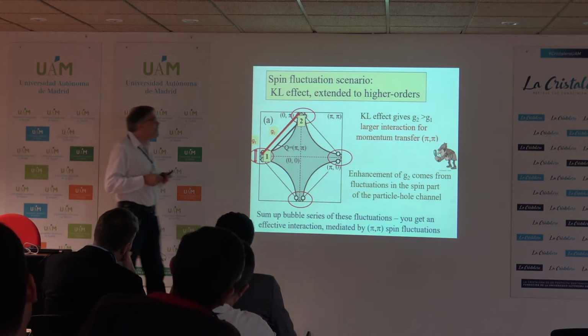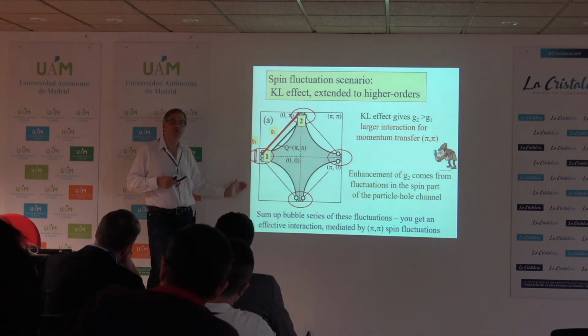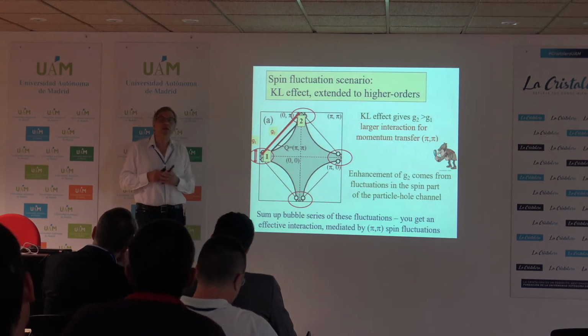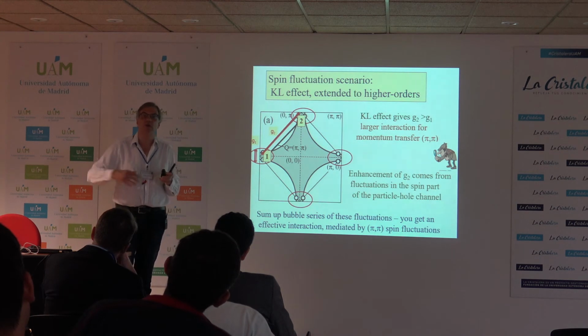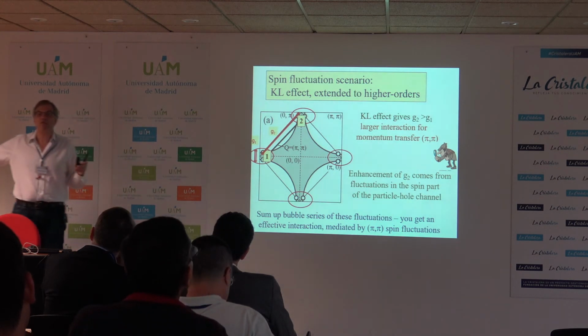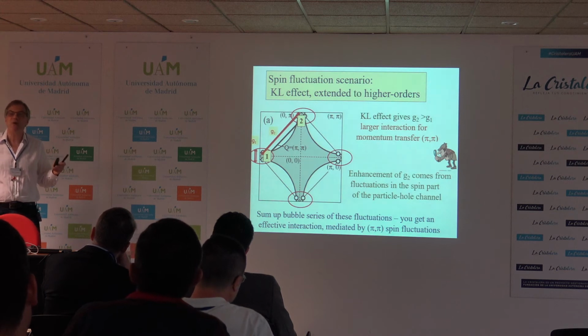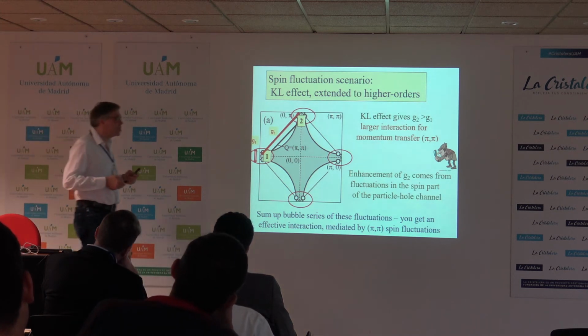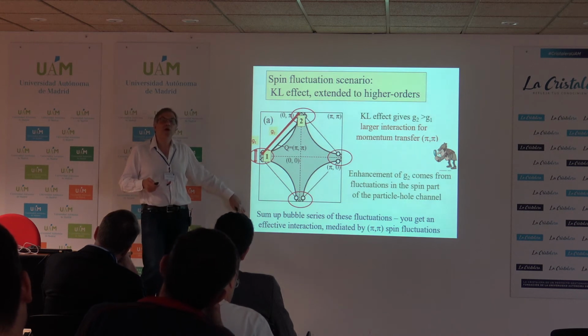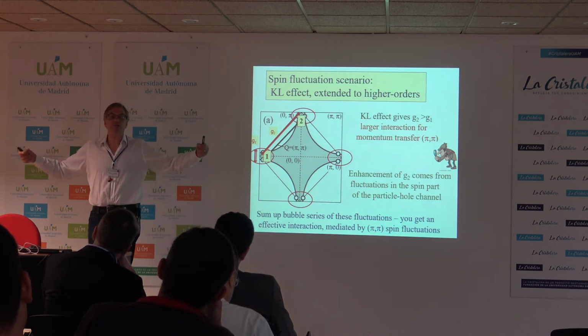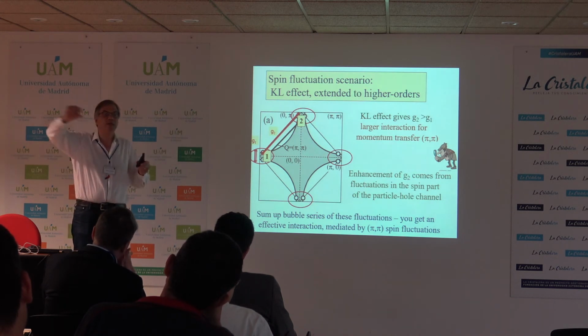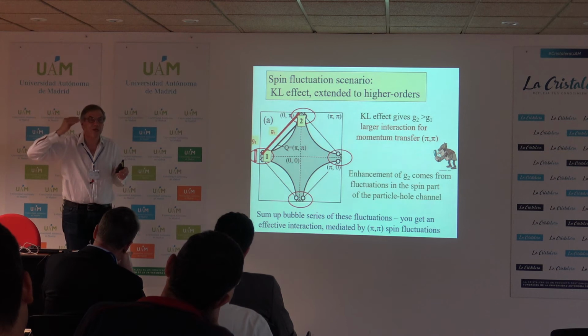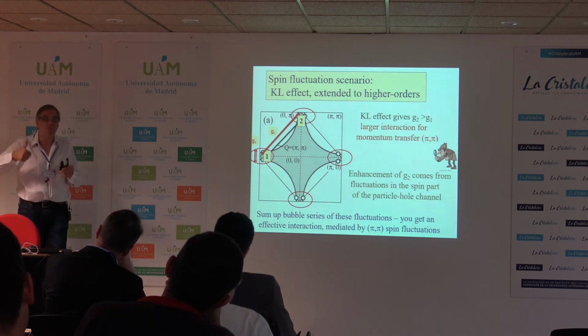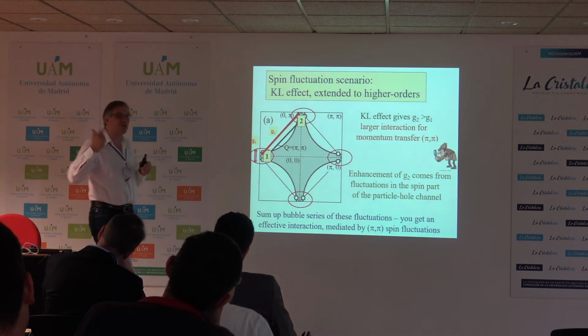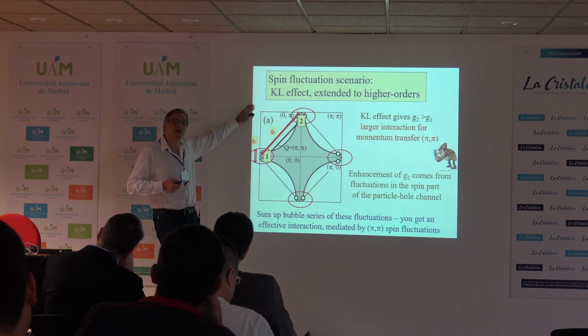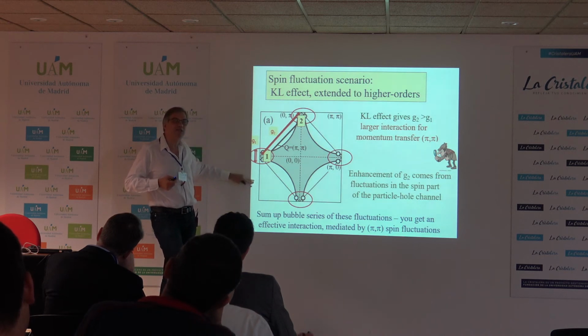So the original idea of the spin fluctuation approach was: well, if it's the case, why don't we go beyond second order and just sum up a bubble series of diagrams like we do in RPA for screening of electron-electron interaction. And then effectively, if we do this, we end up with an interaction between two fermions mediated by the sum of renormalization in the particle-hole channel, which can be equally phrased as mediated by collective excitations in the spin channel, which are spin fluctuations. So in this respect, the spin fluctuation scenario is Kohn-Luttinger taken to infinite order.